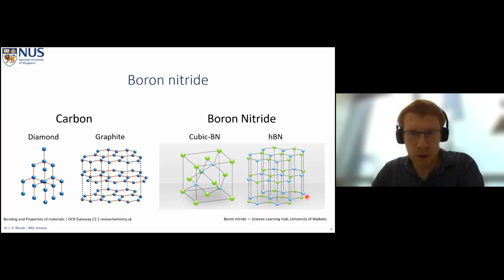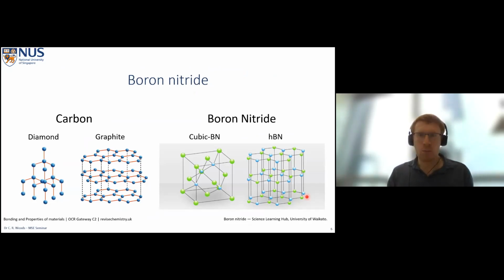Well, in fact, before I mention that, I should mention that because it's made of boron and nitrogen, which sit either side of carbon in the periodic table, it forms isoelectronic structures to those that we see for carbon. So where we have diamond in carbon, the tetrahedral stacking, we have cubic boron nitride. And while diamond is the strongest material in existence, cubic boron nitride is the second strongest material in existence. We also have graphite for carbon, the layered structure, which we can cleave down into graphene. For boron nitride, we have hexagonal boron nitride, which is, again, a layered structure, which we can cleave down to atomic layers.